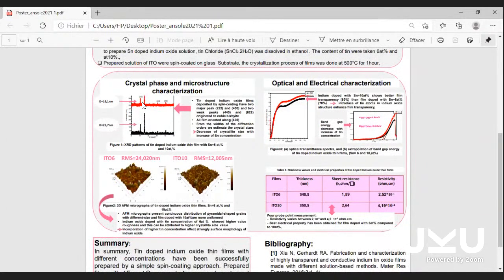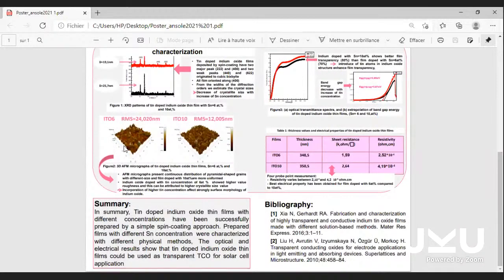For the results, from the XRD pattern we see two major peaks, 222 and 400, attributed to the cubic bixbyite structure, and all films are oriented along 400. We also noticed a decrease of crystalline size with the increase of tin concentration. From the AFM analysis, the 3D micrograph presents a continuous distribution of pyramidal shaped grains with different sizes. We noticed that the roughness of indium oxide doped with 6% showed a value of 24 nanometers compared to 12 nanometers for the film doped with 10%. The incorporation of a higher concentration of tin strongly affects the surface morphology of the indium oxide structure.